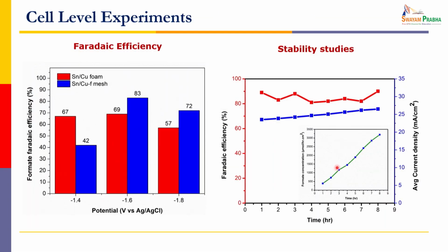And we are comparing this. I've taken one of the earlier slides to show. We have compared the same catalyst on two different substrates: a flat surface, and a mesh. The mesh is more porous, and on that we have made a foam, so that is giving the highest Faradaic efficiency. Close to 83% Faradaic efficiency is obtained for formate conversion.